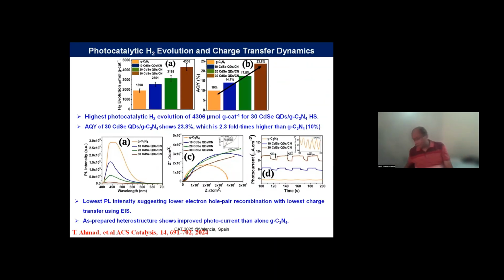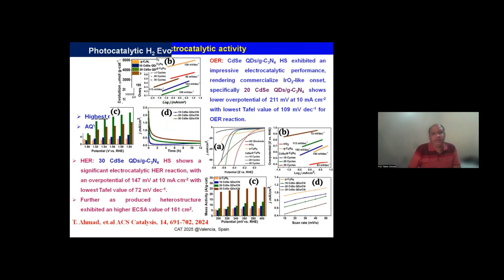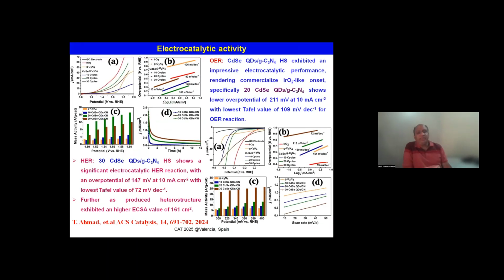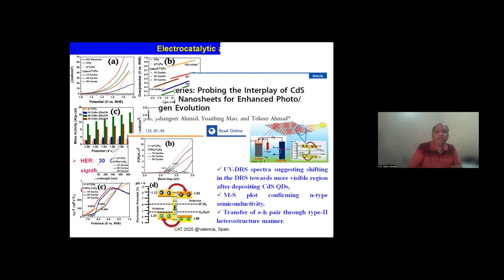Here, the 30 SILAR cycles of the cadmium selenide quantum dots is able to produce 4.3 millimole per hour per gram of hydrogen with an apparent quantum yield of 24%, which was supported by other investigations like EIS, photocurrent plot, and PL investigations. Then the 30 SILAR cycles of the cadmium selenide quantum dots on graphite carbon nitride is giving the significant HER reaction, which was supported by the high electrochemically active surface area.